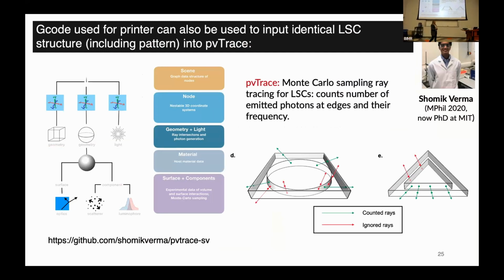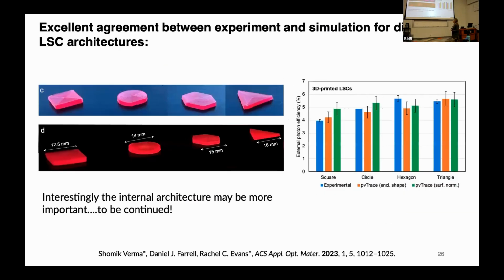One thing that Shomik found out, Shomik was an MPhil student doing a year with us during COVID, and he's a very smart young chap who's now at MIT doing his PhD. He realized that the G code that we use to talk to the 3D printer can also be integrated into a Monte Carlo ray trace modeling program that is commonly used to predict the efficiency of LSCs. So what this allows us to do is put in the exact design, including the line structure of our proposed printed part, model the performance, and then if it looks promising, print the part and see if the actual performance lives up to the predictions. And that's exactly what we find out.